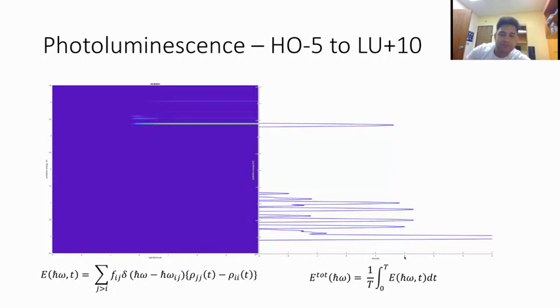So the Y axis is excitation energy. It ranges from -0.5 to 4.5 eV. The bottommost peak on the intensity graph is right about at 0, and the top peak is right around 3.3. And for the blue graph, we're looking at a logarithmic time scale going from -3 to 4. And in the intensity, we're looking at a logarithmic intensity scale going from -3 to 5.